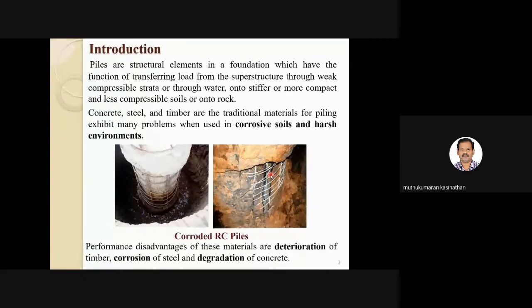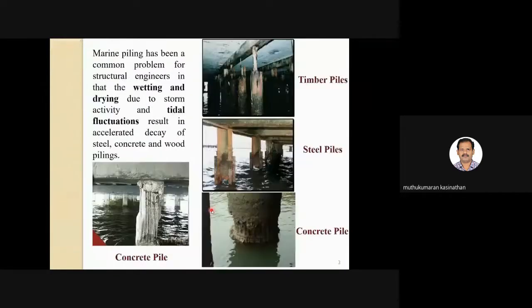But after installation, sometimes we may have problems related to the pile. You can see classically how it has happened. Your cover concrete has completely spalled, the reinforcement is exposed to the open environment, and oxidation easily takes place, which accelerates the corrosion of the steel in the pile concrete. So finally, you'll end up with a very reduced pile capacity, or the pile may fail over a period of time. So this is a challenge.